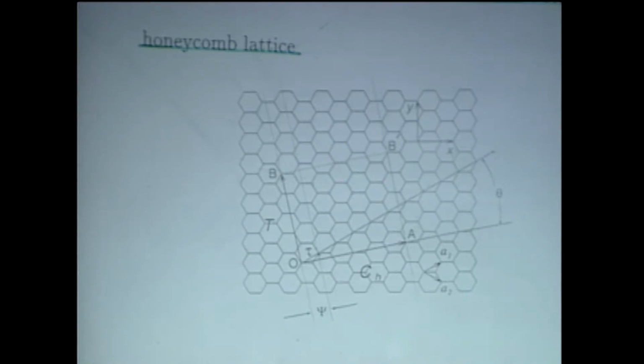That's not unique. And if I now drop normals like OB or AB prime to the line OA, then I have the lines that I have to join. So that shows you that there's a whole family of these tubes I can make. They have a different property in that they're chiral. That is the atoms wind around in spirals as they go up the tube, rather than just circles for the simple cases that I mentioned before. But there's a whole family of them. And what's most remarkable about these tubes is that 1/3 of them are metallic, and 2/3 of them are semiconducting, depending on geometry. So that's a very interesting thing. And I'll give you a very brief summary about why that comes about, but I can't give a very simple display of that.